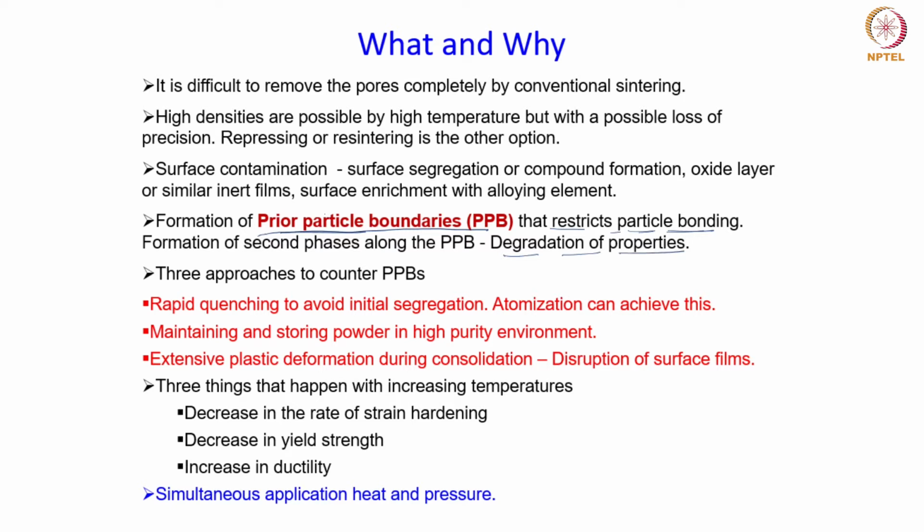First, rapid quenching can be adopted to avoid the segregation. And with regard to that, atomization is a process which can achieve this, because we have seen that the cooling rate in the atomization process is higher compared to many other powder fabrication techniques.